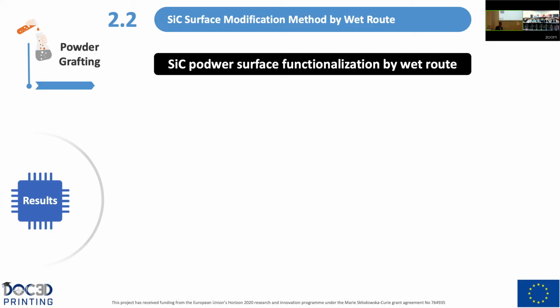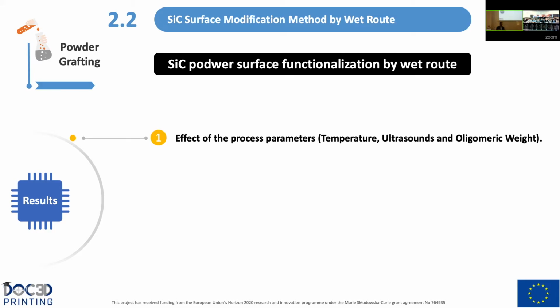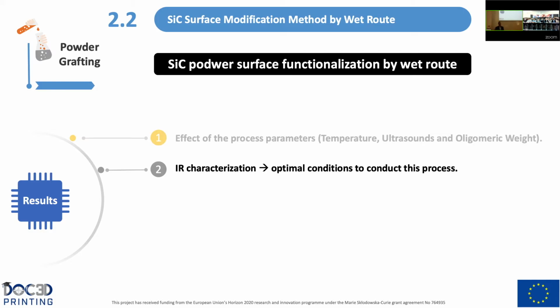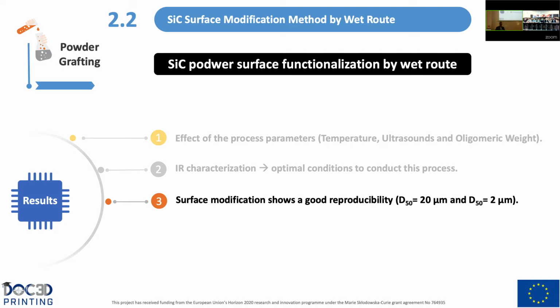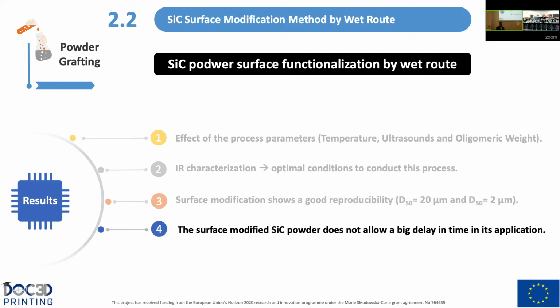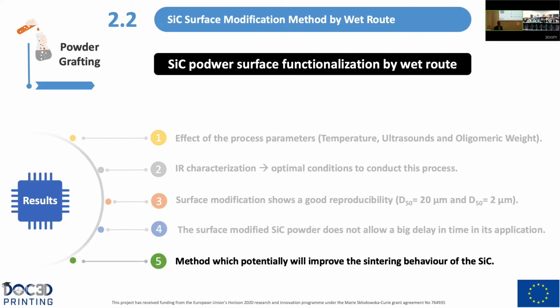So regarding the results of this part, we have studied the effect of the process parameters: temperature, ultrasound, and oligomer weight. We have used infrared characterization to study the optimal conditions to conduct this process. Next, we have observed that the surface modification shows good reproducibility. We performed this surface modification on 20 and 2 micrometer silicon carbide powder. Actually, the surface modified silicon carbide powder does not allow a big delay in time in its application. And finally, this is a method which potentially will improve the sintering behavior of the silicon carbide, as we will see in the following section.